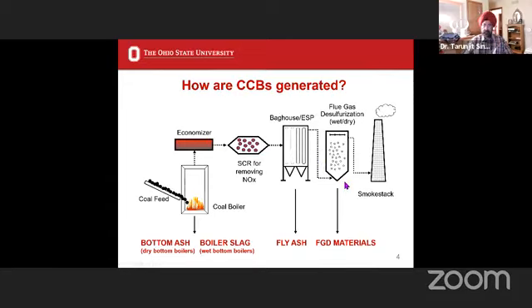And in much of the US, especially in the part of the US where I am, the sulfur content of the coal is quite high. It is high sulfur coal. As a result, one has to use a desulfurization process. In general, one would do a dry or a wet injection of some sort of a calcium oxide combination, magnesium oxide mixture, some sort of lime solution or dry is injected. And there are two further ways in which this FGD or flue gas desulfurization material can be generated. If you are not doing forced oxidation, then we will have a sulfite material. And if, on the other hand, one is doing forced oxidation, then one ends up with a sulfate material, which would be FGD gypsum.